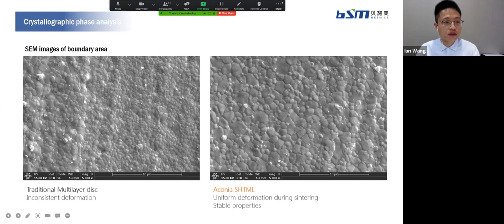And there are 2 similar images of the boundary area. The left one is the traditional multilayer disk. And from the microstructure, we can see there is a boundary between the big particles and the small particles. So we may know for this blank, during sintering, it may get an uneven deformation. But for our SHTML, we can see because of the layer blending technology, it has a very homogeneous particle size distribution. So we can know it can ensure the uniform deformation during sintering, and also it can ensure the stable properties of this blank.